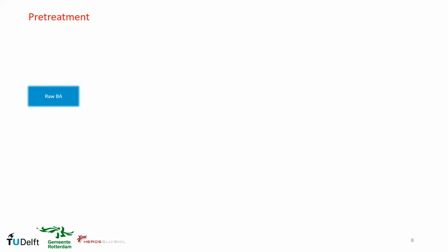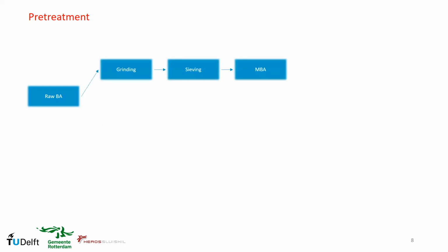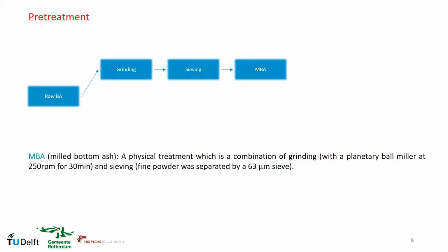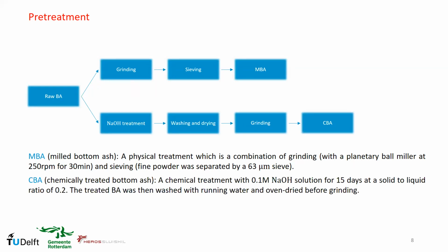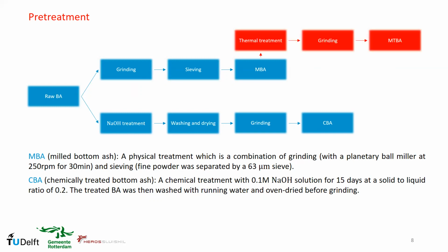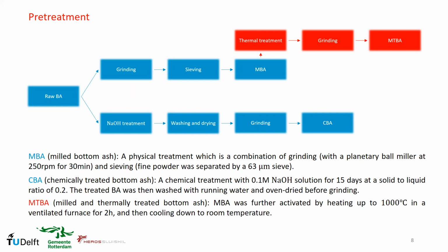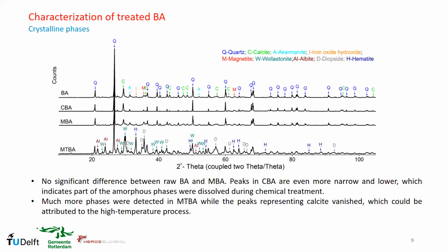So in this study, we have three types of treated bottom ash samples. First, the MBA by a physical treatment combining grinding and sieving. Second, the CBA, the chemically treated bottom ash with 0.1 molar sodium hydroxide solution for 15 days at a solid to liquid ratio of 0.2. The treated bottom ash was then washed with running water and oven dried before further grinding. And finally, we found that the MBA is not reactive enough, so we further performed thermal treatment on MBA at 1000 degrees in a ventilated furnace for 2 hours and then cooled it down to room temperature.